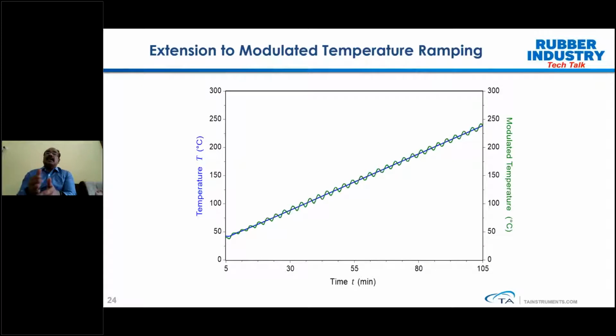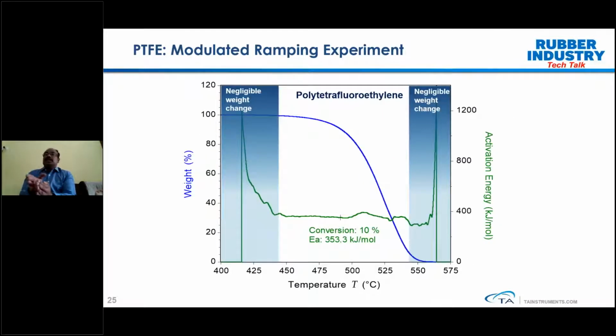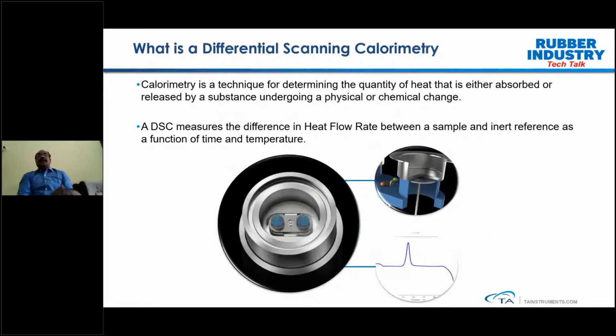The way it works is that instead of applying a standard heating rate, we apply a modulated temperature ramp, in a sinusoidal fashion. Then there is an algorithm which will plot the activation energy, like in this current thermogram. What you see is polytetrafluoroethylene. So we can see a simple step change, and then we plot the activation energy in real time. As the sample undergoes the decomposition, we can see at what conversion percent, what is 354, the activation energy of that particular sample. So that's about the advanced techniques on the TGA.